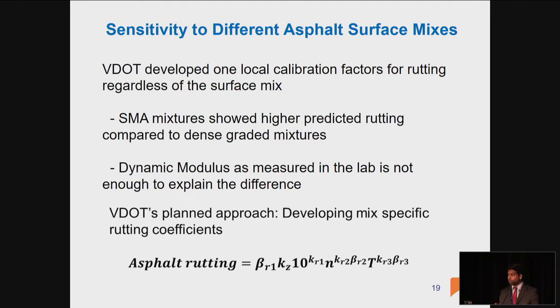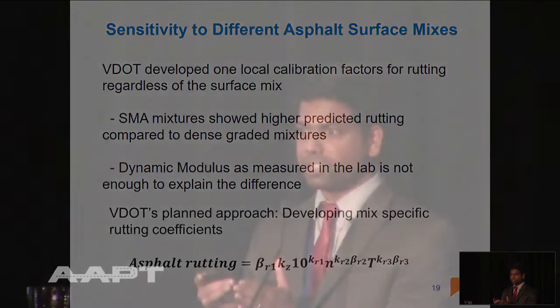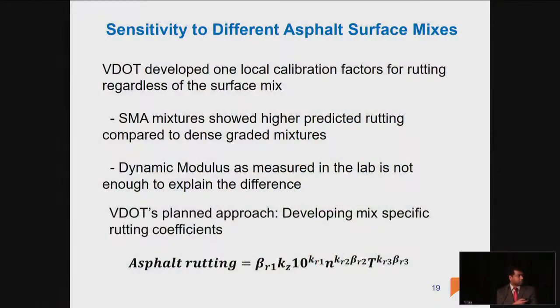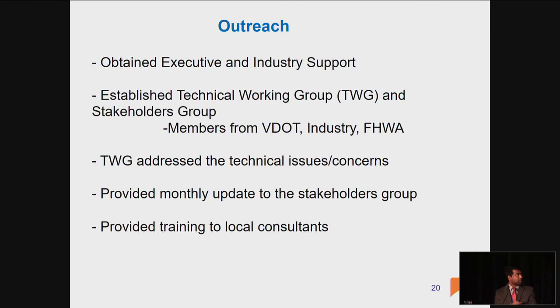The other thing is sensitivity to asphalt mixes. We developed only one calibration factor for the asphalt mixtures. When we use SMA mixtures, it predicted very high rutting. So that is against our field experience. This is because usually SMA mixtures have higher binder content, and when you test in conventional dynamic modulus testing, it gives lower modulus. So in turn, it will predict higher rutting. So we plan to develop mix-specific coefficients for SMA in the future.